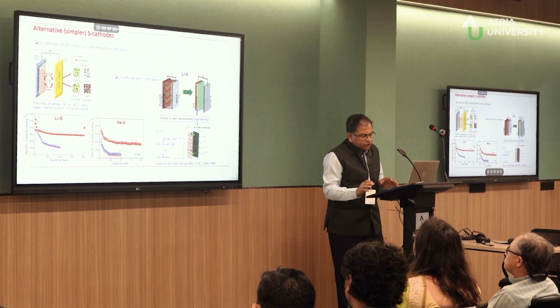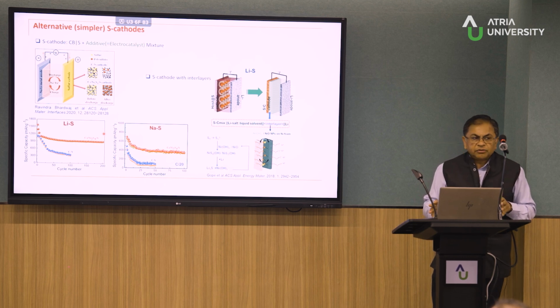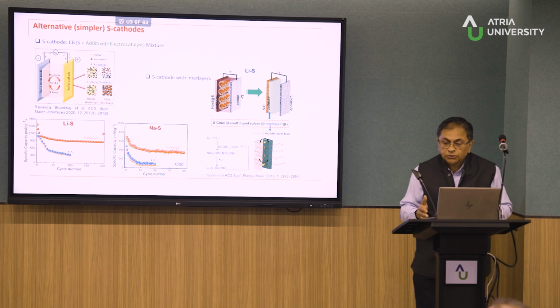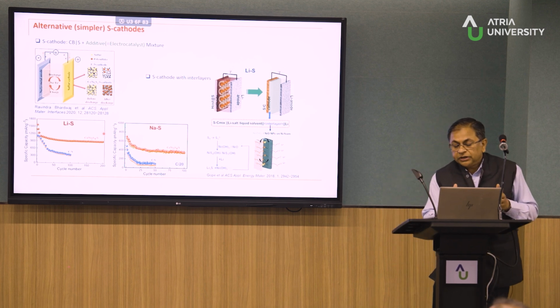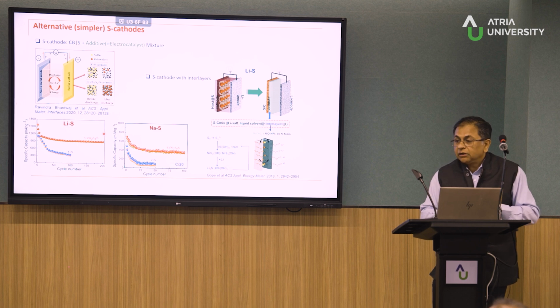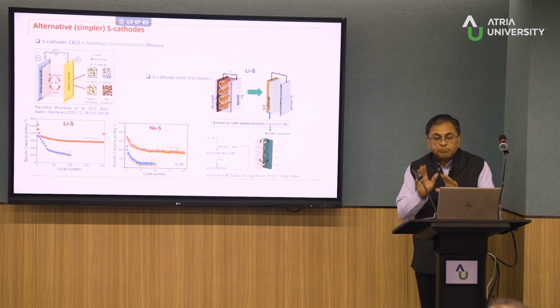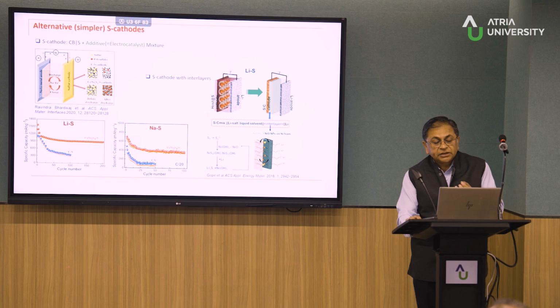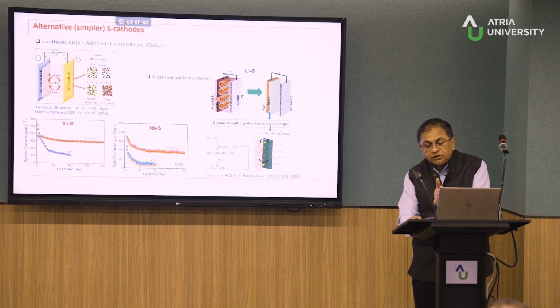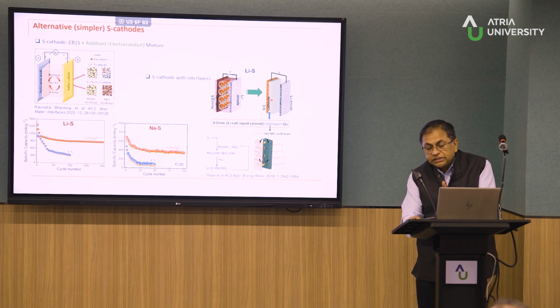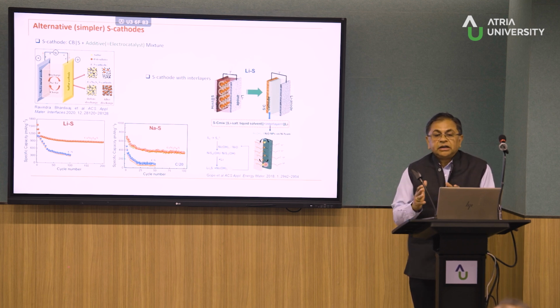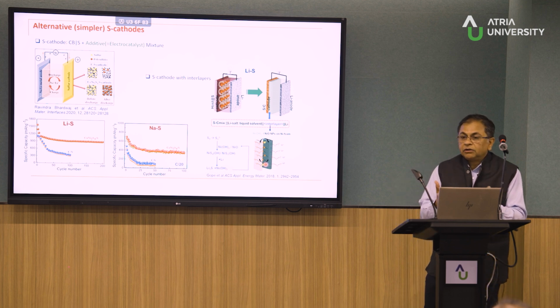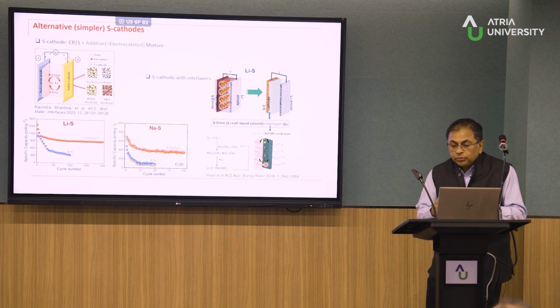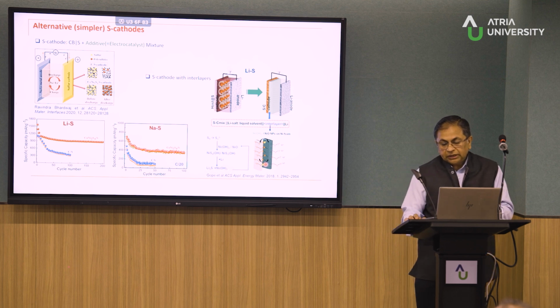This is something which around this time Professor Manthiram had a lot of papers on, using interlayers, but they were all based on carbon. So what we did was, right, we did not take carbon, we took nickel oxide. All right, this does the same thing. Now, what we are doing here is, instead of having everything on the sulfur cathode, you shift the center of action from the sulfur cathode to an interlayer, which is basically a separator with the nickel oxide coated.